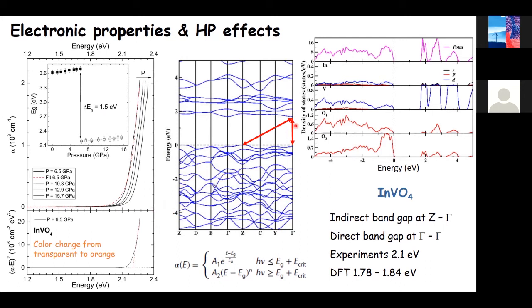The calculation predicts this band gap to be around 1.8, which is a reasonable comparison to the 2.1 value of the experiment. And we have 2 band gaps, one direct and one indirect, very close in energy. As when we have this phase transition, there is a very important increase of hybridization between vanadium and oxygen states, and this is what produced the collapse of the band gap.